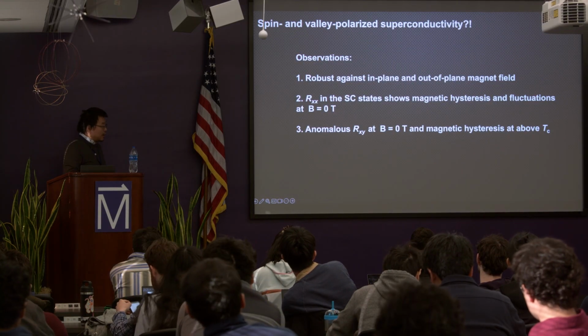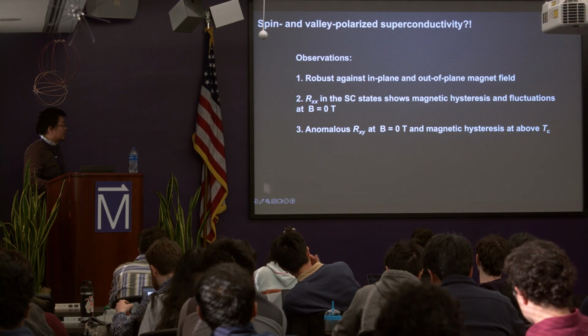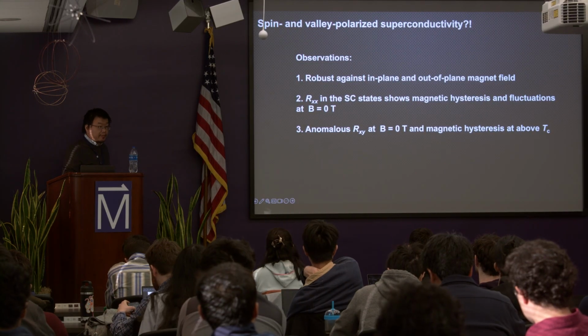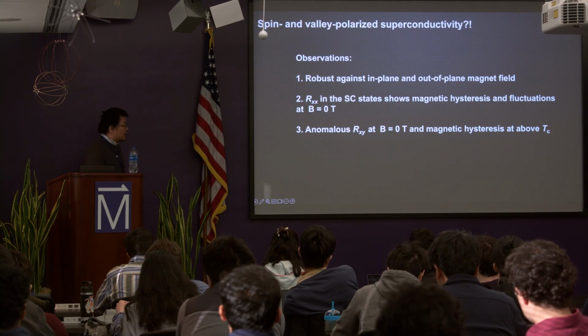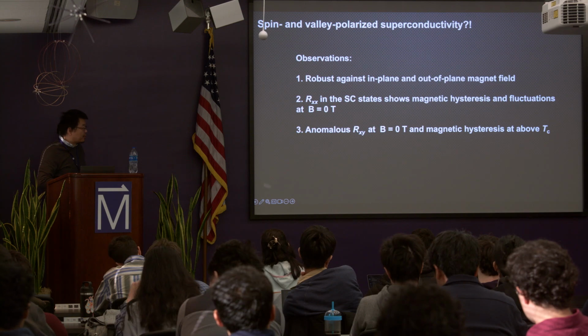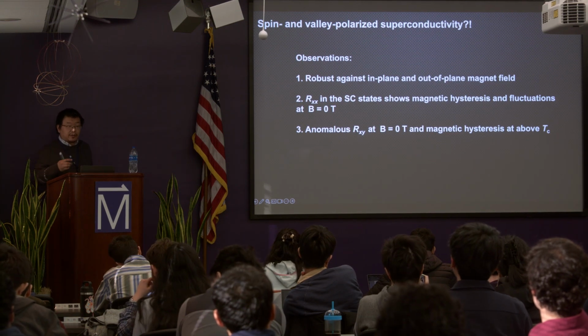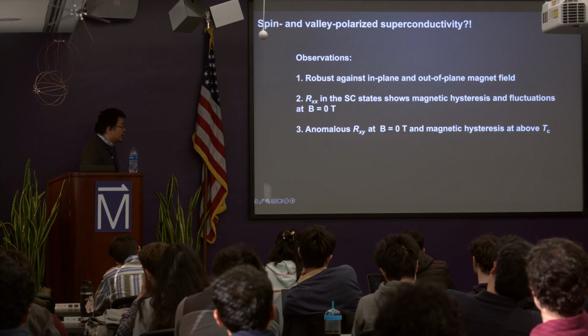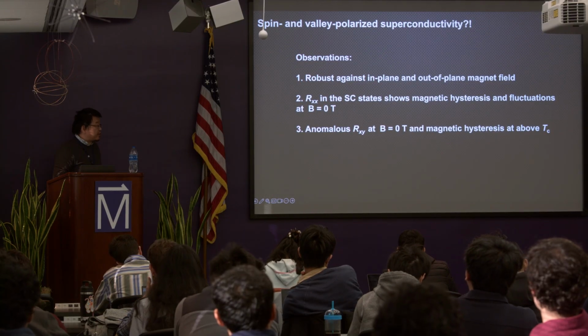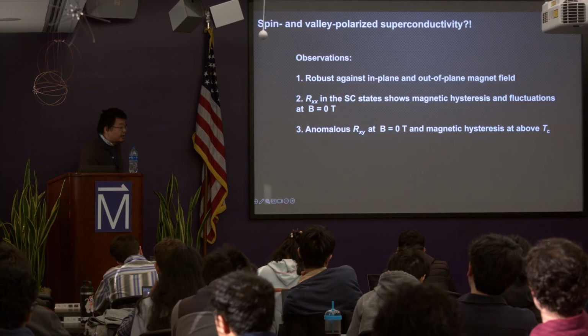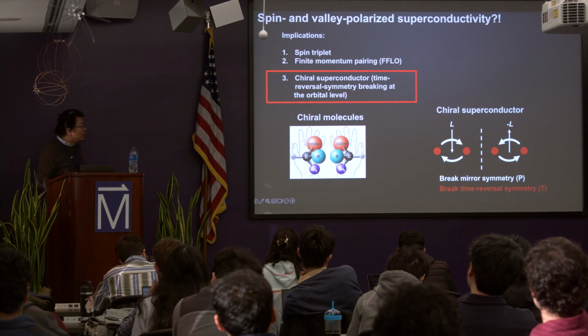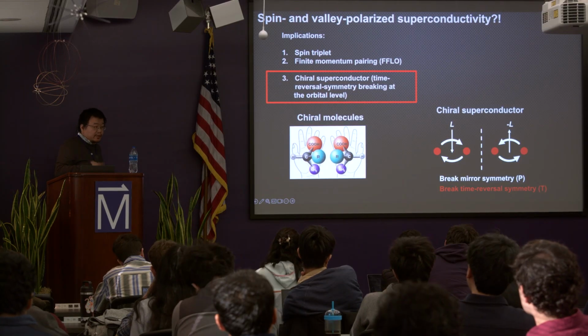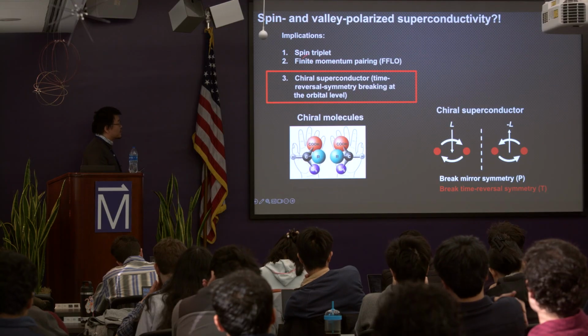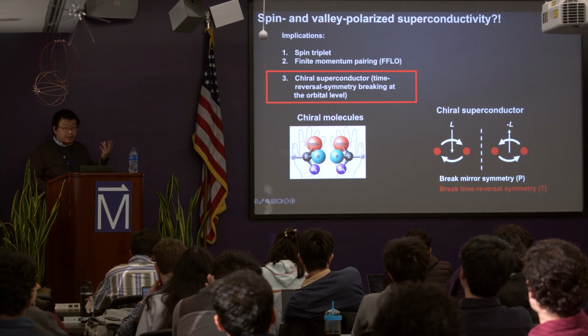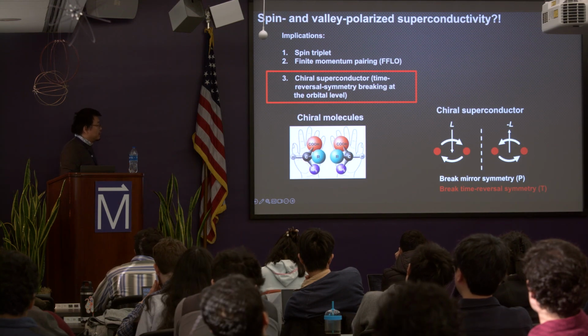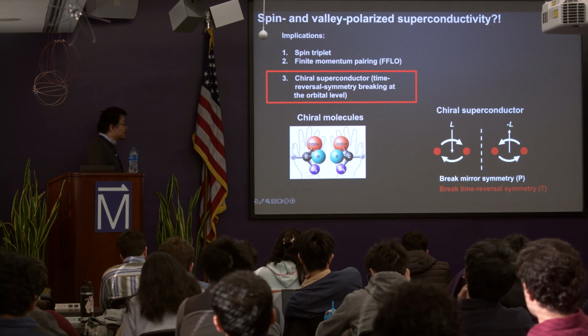So, a little summary of what we see: the superconductivity is pretty robust against in-plane and out-of-plane magnetic field. We do see magnetic hysteresis and fluctuations at B field equal to 0, and you have anomalous Hall effects in the higher-temperature state where you lose the superconductivity, and also in the surrounding states. So basically, they suggest you may have a superconductivity that comes from a quarter metal. This is already suggesting a lot of things. It suggests a spin triplet. And because the pairing is coming from a single valley, it's definitely FFLO. And because it's coming from either the K or K prime valley, it's naturally chiral.